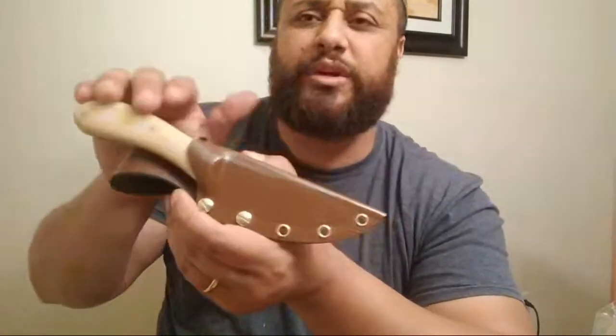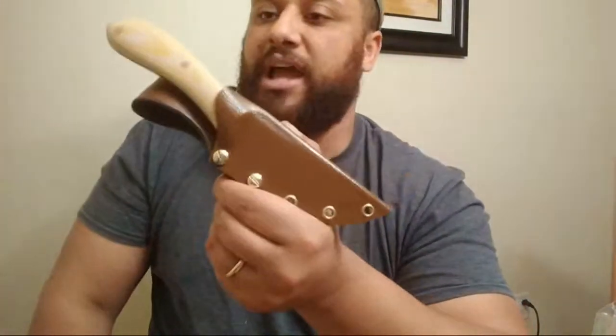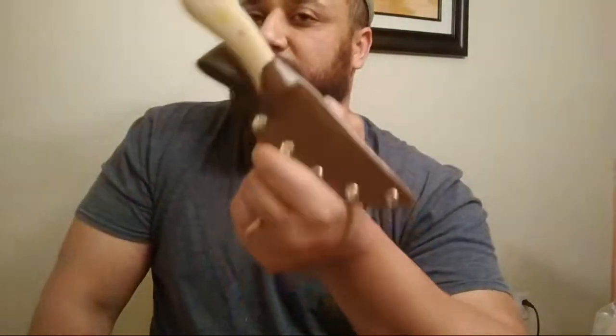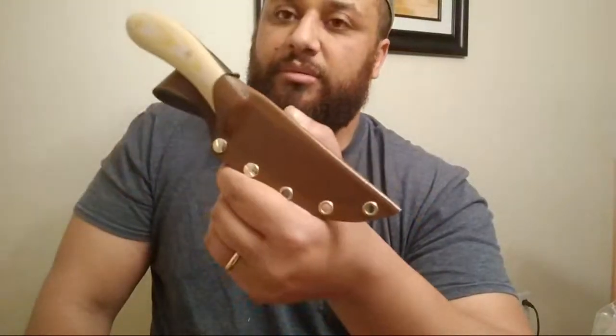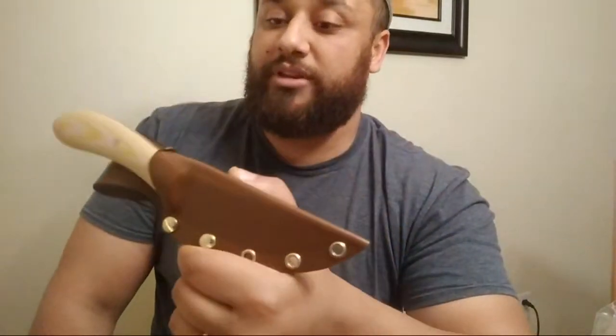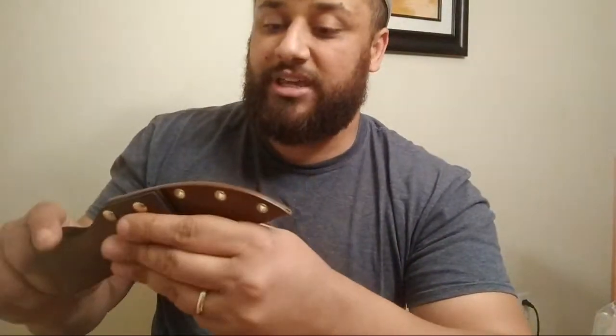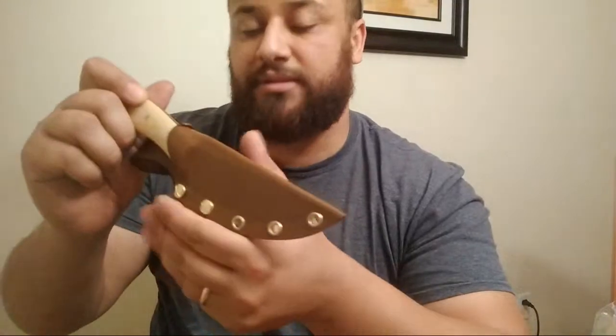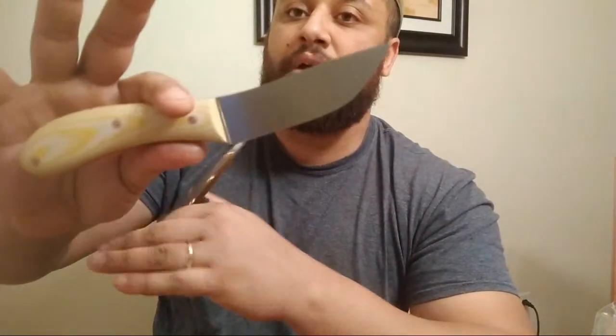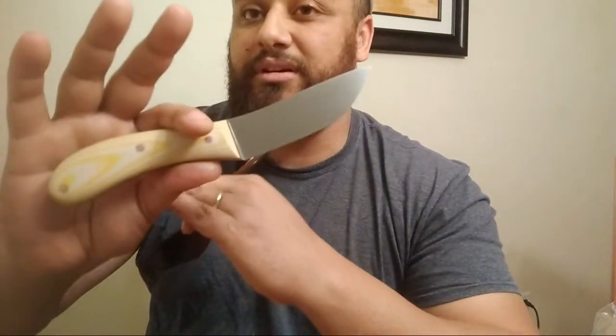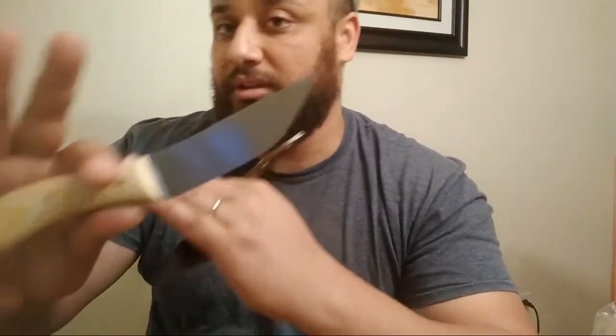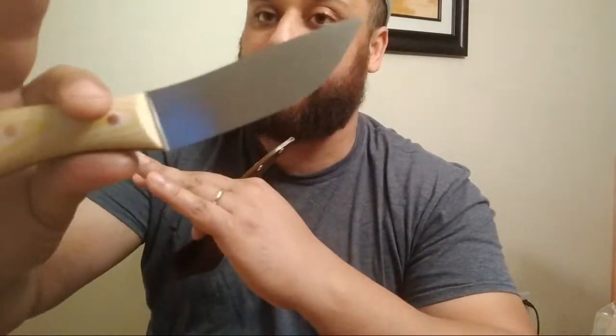We have a special heat treat on this one. I wanted to focus more on solid solution strengthening with this material and have it at a high hardness. I didn't like the idea of doing precipitation hardness to try to get this material to work well. I wanted my matrix to be filled with lots of tempered martensite rather than bleeding it all out to M2C and M6C, so I felt it was more stable. I did some impact testing with this material. It seemed like with the austenitizing and tempering temperatures we were using, we got a lot more stability compared to the guidelines used in industry for making parts, which is what the steel was designed for.